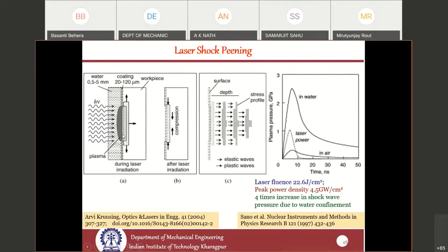This black coating readily absorbs the laser power and gets heated up, forming fume and plasma. This plasma tries to expand, generating a lot of pressure. This expansion is confined or restricted by the water layer. Therefore, compared to air, in water it generates 4 times more shock wave or plasma pressure. This pressure propagates inside the material, and when it increases the compressive stress beyond the dynamic yield strength of the material, it causes plastic deformation, introducing a good amount of compressive stress.